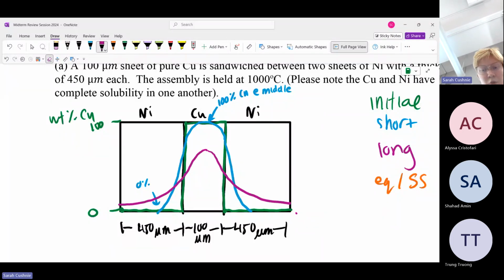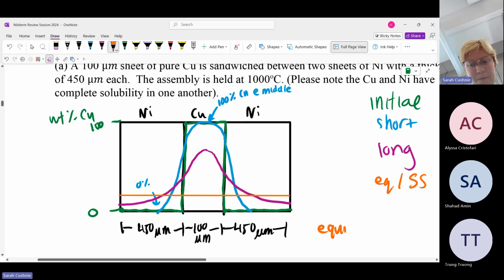Now you may ask, why do we no longer have 0% copper at the edges? That's a really big factor. We've moved up, they're no longer at 0, and that's because the copper is now diffused throughout the entire block. It's reaching the edges of the nickel. Then long term, this is slowly going to homogenize as the copper diffuses more into the nickel, and we're going to end up with something that looks like this. This will be in equilibrium because it's all constant, it's all homogeneous.